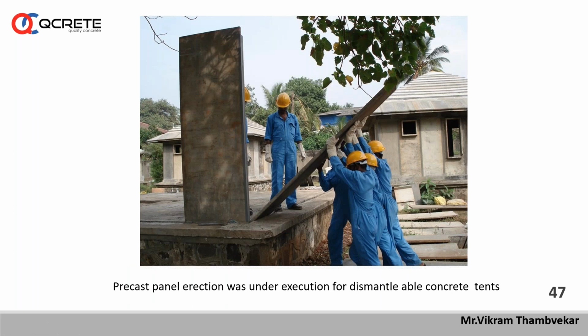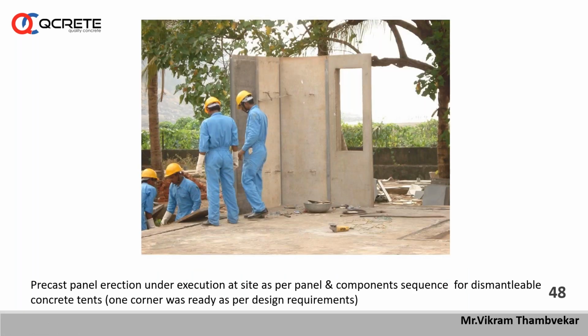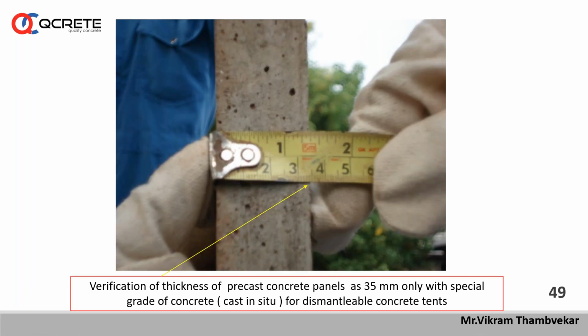In this slide we are showing the vertical components which were cast in a yard and are under erection at site, and in the background you can see other structures already erected properly as per the different components. In another picture we can see this corner portion is ready, erection is going on, and this corner area is packed or erected in part, and behind that you can see the sea. These particular tents are facing the sea. In this slide we can see the thickness of all these wall panels is only 35 mm, not more than that.